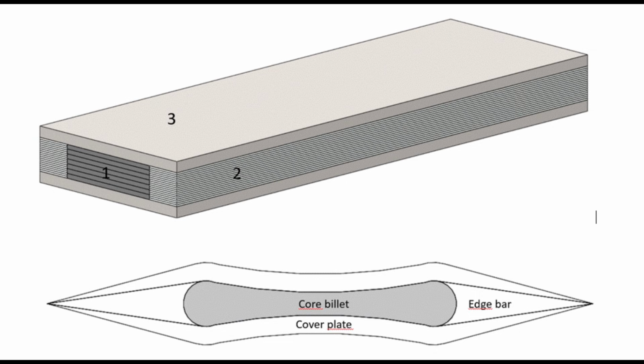Most likely one of them is primary bloomery material and the other one is a refined steel, which are both forge welded together and then folded and welded back on itself around 4 times. This gives the layer appearance that we see in the blade, and that means that the core interior is made of a composite laminate material of iron and steel, made in very thin layers.